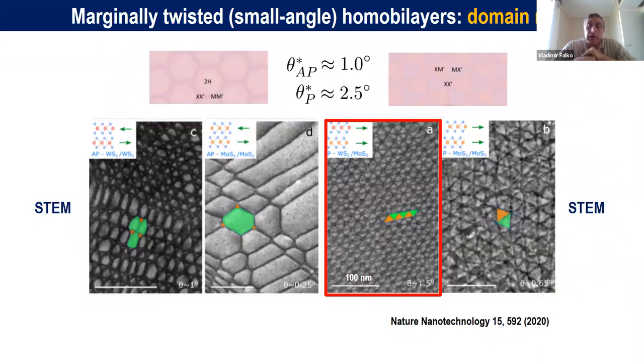When it's looked at in transmission electron microscopy, what you see here are the domain walls, because that's where the variation of the local stacking takes place. Inside the domains, transmission electron microscopy does not give information, for example, whether it is MX or XM stacking, or the polar orientation of the unit cells of the crystals. What you see in the two examples on the left-hand side is a sequence of hexagonal-like domains with 2H stacking separated by dislocations. And on the right-hand side, for parallel orientation of the unit cells of the two materials, you see the triangular network of domains and domain walls, with the dots here representing the stacking which corresponds to chalcogen sitting on top of each other.